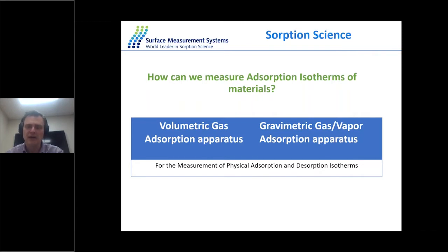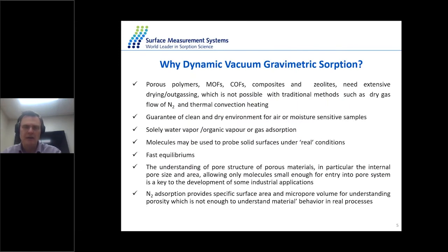And most of the adsorbents are used at atmospheric pressure or higher pressures, at room ambient temperatures or high temperatures. So you're not going to use the zeolites at 77 Kelvin. Now, there are many gravimetric sorption analyzers, and they usually operate at atmospheric or ambient pressure. What it means is they have nitrogen and air as a carrier gas, which is also then used for generation of the vapors. But in many cases, these porous materials require high temperature and high vacuum to be completely outgassed, to remove completely any adsorbed molecules. And this can only be achieved in a vacuum system, when you can apply vacuum at high temperature, because traditional flow methods and conventional heating are not sufficient. So when you use nitrogen, you're basically pushing the molecules, and it's not as powerful as when you're pulling the molecules when you use the vacuum.